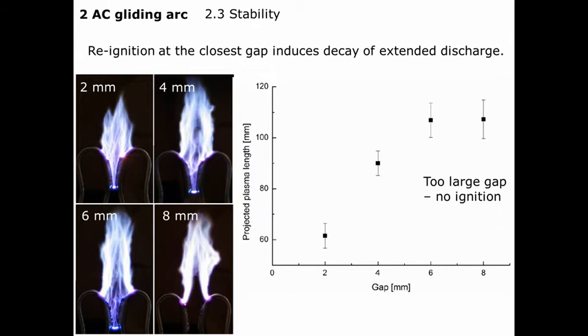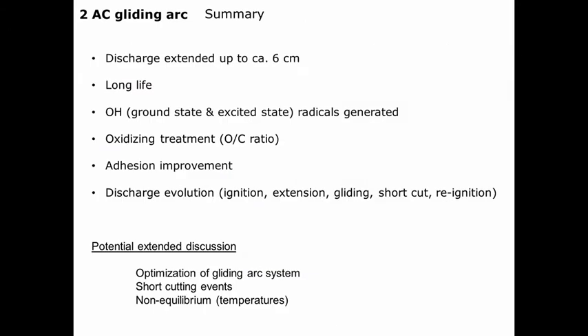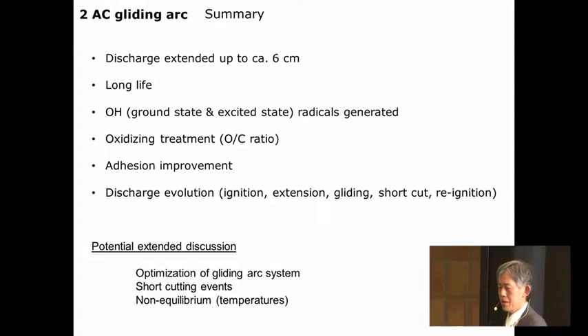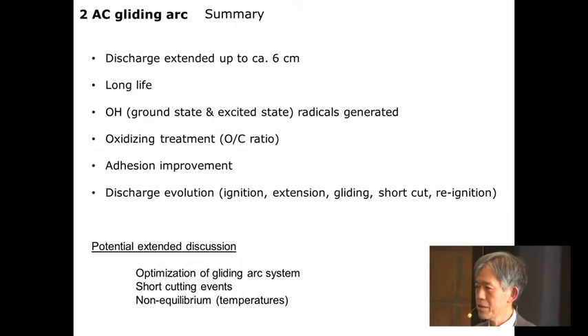And as distance is increased, the plasma tends to be elongated. But if it is too much, obviously we cannot have a discharge because of the requirement of higher voltage. So there must be an optimum gap. But maybe I would leave this for further discussion if necessary. And I demonstrated long life duration of the plasma, long extension, and OH radical generation for surface modification, and improvement of the mechanical properties in this.